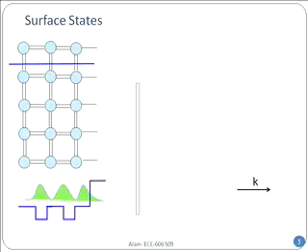So when you solve the Schrodinger equation for this problem, the Kronig-Penney equation for this problem, not only will you get normal bands, conduction band, valence band and all those, but you will in addition get bands in which there will be extra levels. These are called surface states. Now this is very different from trap levels, right?